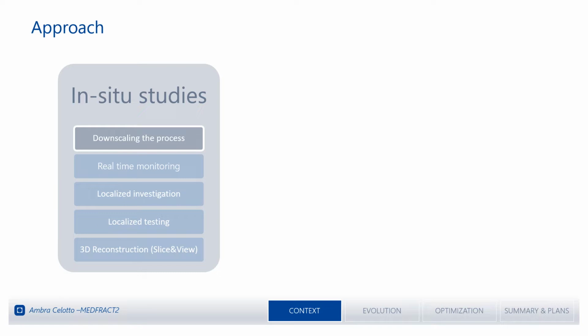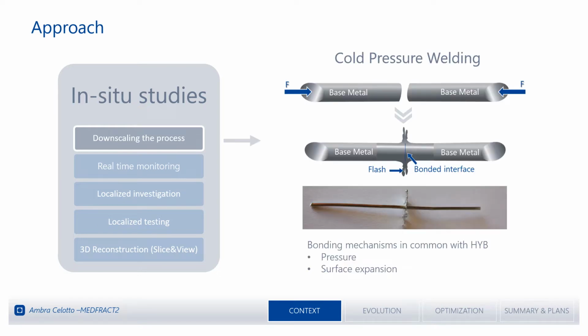Therefore, we took example from another solid-state welding technique called cold pressure welding. This method consists in putting two metal pieces in close contact under a certain load and making them achieve bonding at room temperature. This method is well known for exploiting two of the several bonding mechanisms going on in the HYB process, which are pressure and surface expansion. So we will use this technique as the main inspiration for developing our new microscale technique.